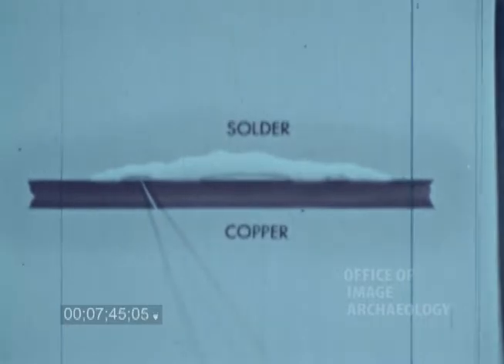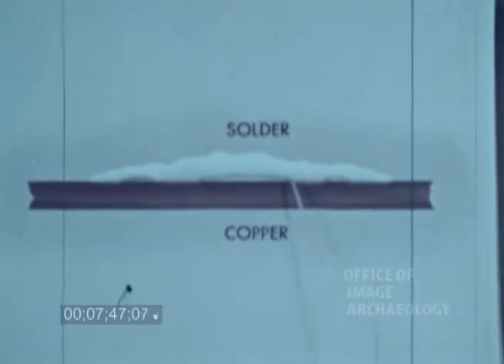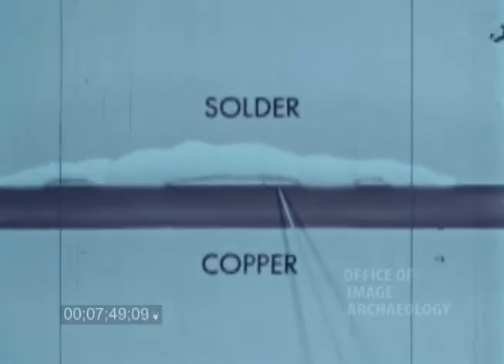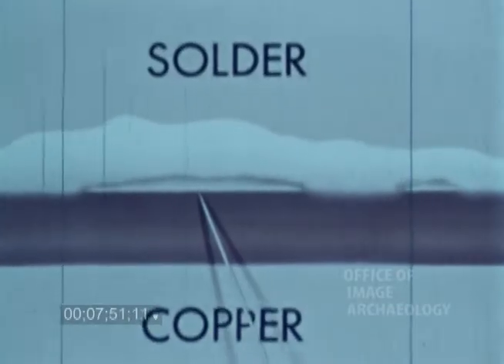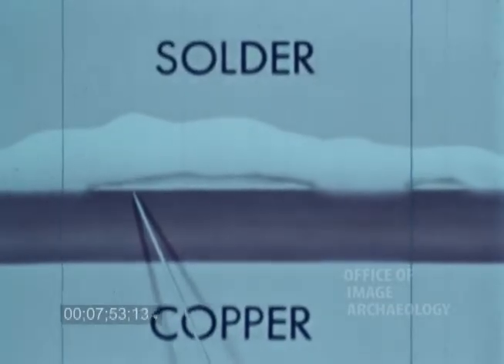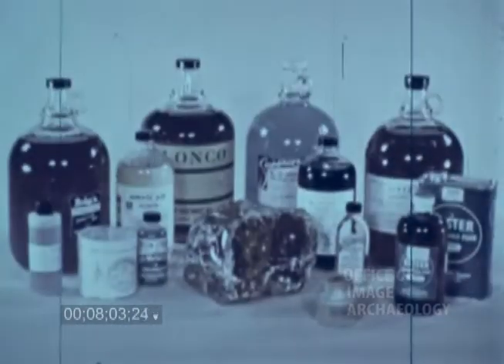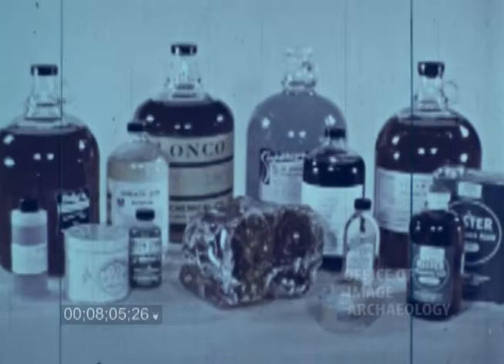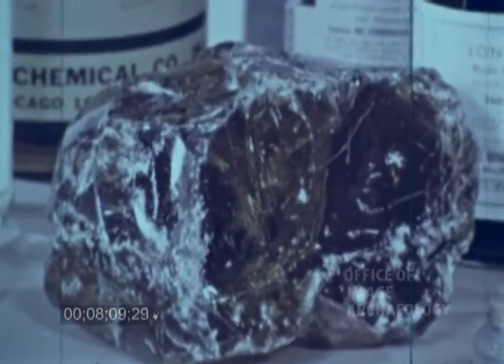So even though our metal had been cleaned thoroughly beforehand, the oxides in these areas formed while we heated the copper and prevented the solder from bonding. These oxides must be removed or prevented during the solder operation. For this, we use chemicals called fluxes. There are many types of fluxes. However, only those derived from natural rosin are acceptable in soldering electrical connections.